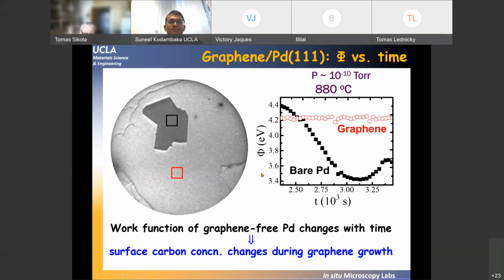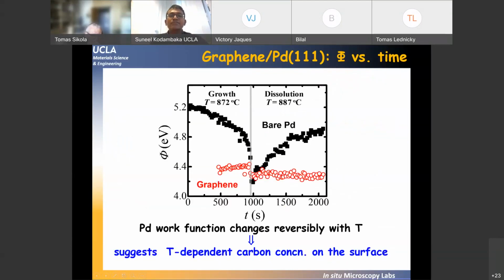Anytime there is a change in work function, and you know the environment is vacuum so there is nothing being added, it indicates that something is changing on the surface. In this case, we know that there is carbon segregating onto the surface, so there must be a carbon-induced change in the work function. It turns out that there is a significant accumulation of carbon, and this behavior is repeatable. During graphene growth, the work function decreases. And if you start heating it, as the carbon goes back in, the work function almost recovers.